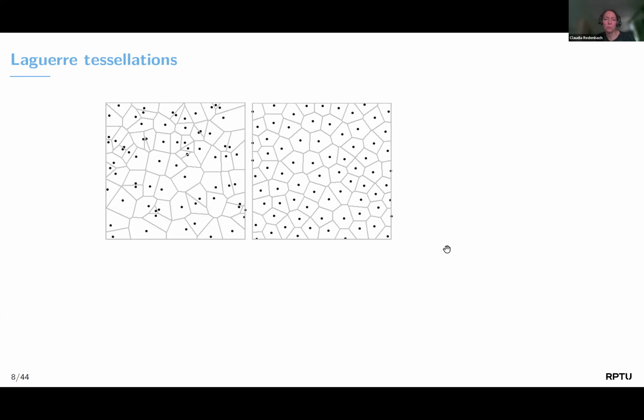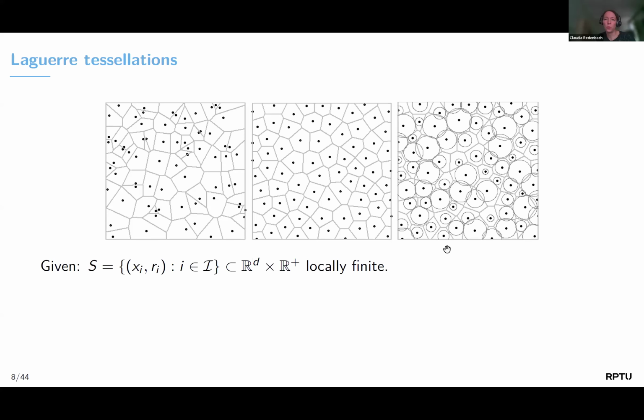Here we see so-called hardcore point processes. In the hardcore point process, the points are not allowed to get arbitrarily close. And you see immediately the cells look much more regular. Now, if you also want to control the cell size distribution, you could go one step further and attach a weight to each point, here represented by these circles, with the idea being the larger the radius of the circle is, the bigger the cell should grow. And this gives you another degree of freedom that could be used to describe not only the cell shape, but also the cell size distribution.